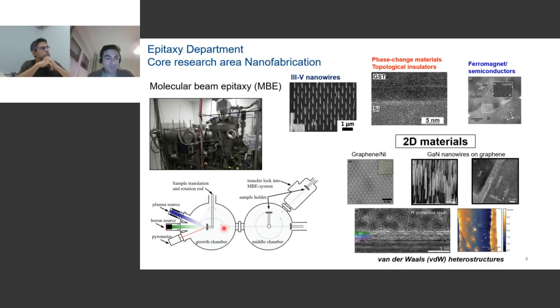And this beam of the material that you want to deposit is just hitting the sample, right? And well, we can also use plasma sources. In the case of boron nitride, we have the nitrogen gas going through the source, and then basically you generate a plasma, and this would be then the source of nitrogen. And of course, you have other ports where you can, for instance, monitor temperature through an optical pyrometer and so on.